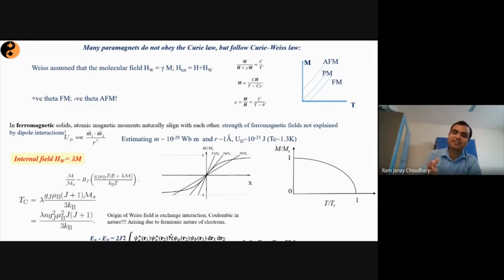And if your J is negative, then the triplet energy state goes up and ES comes down. That means your spin singlet is stable. That means your antiferromagnetic state is more probable. So that is how this internal field or the molecular field is related to the exchange interaction between the two electrons, where you just exchange the position of the individual electrons, and you get an additional energy state, which is given by 2J square times this integral expression. Okay, and from there we get this kind of idea.